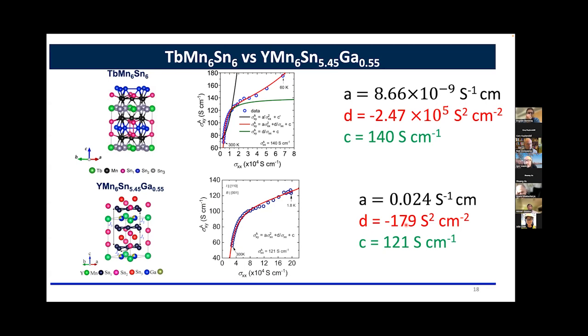Regarding the flat bands, first, they are not very flat because the material has considerable hopping across the level. And, as opposed to the Dirac band, it's not a topologically protected feature. It just appears only if you have a particular model. So that doesn't seem to play much role or any role at all.